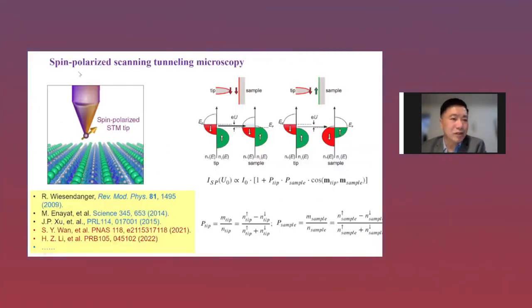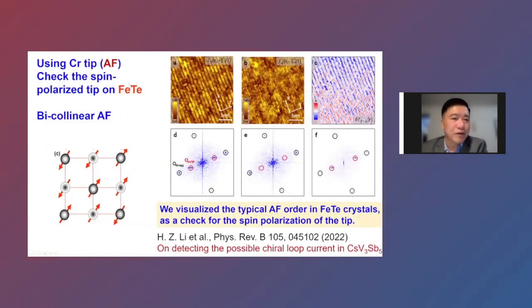Then we use the spin-polarized STM to measure whether we can see the so-called antiferromagnetic order. We thank Professor Wiesendanger for helping us and giving us some advice to build up this STM with spin-polarized ability. And we published some papers based on that kind of study. So we first characterize the spin tip with so-called iron telluride. And this sample, you know that it is antiferromagnetic, okay, which has a so-called bicollinear antiferromagnetic order. So we measure spin up and spin down topography with subtraction. Then we see this kind of bicollinear structure.